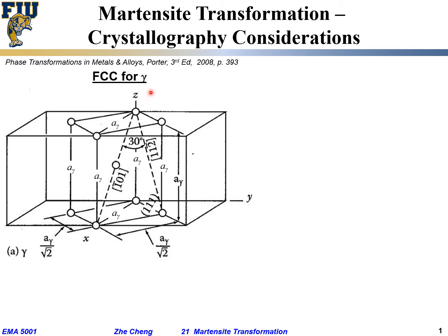What we know is that the higher temperature phase — the gamma phase, or austenite for iron — has an FCC, or face-centered cubic structure. What we have here shows part of a unit cell for the FCC iron structure, with x-, y-, and z-directions. Atoms are represented by open circles at the corners and the so-called face centers. For simplicity, some additional atoms are omitted, but essentially we show two neighboring FCC unit cells joined together by a plane.